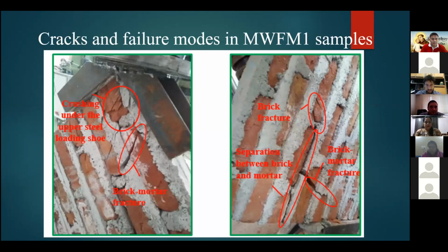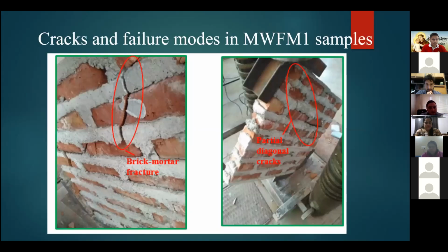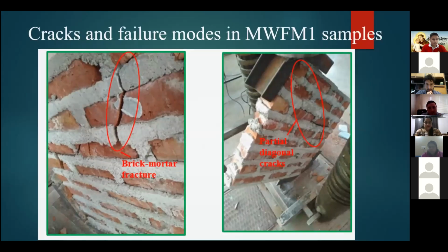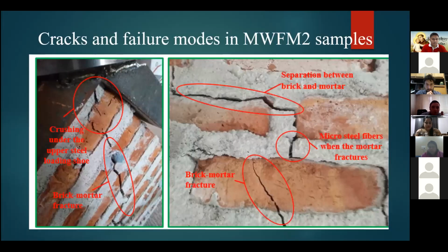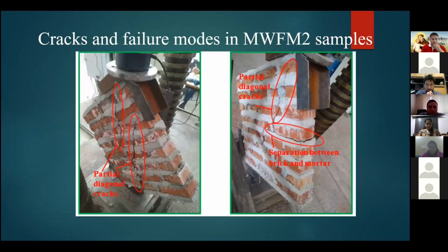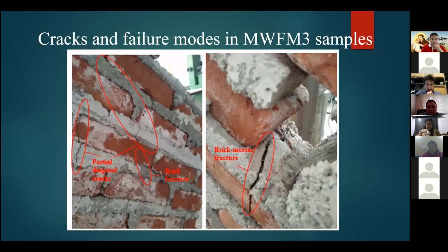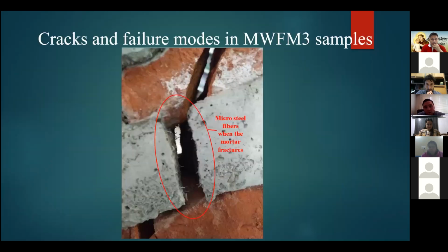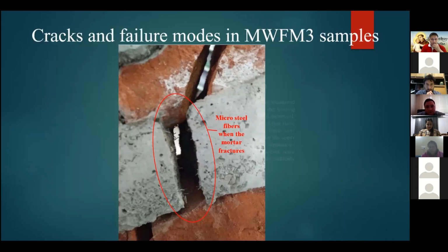Cracks and failure modes in MWFM1: crushing under the upper steel loading shoe, brick mortar fracture and brick fracture, separation between brick and mortar, and partial diagonal cracks. In MWFM2 samples: crushing under the upper steel loading shoe and brick mortar fracture, and microsteel fibers when the mortar fractures, separation between brick and mortar. And in MWFM3: brick mortar fracture, partial diagonal cracks, brick fracture, and microsteel fibers when the mortar fractures.